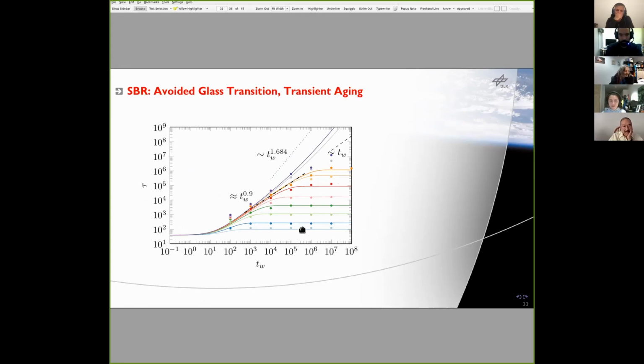And if I do that, basically nothing dramatically changes for the points where I quench to liquid states, because there in the end still ordinary MCT is good enough. But for the quenches into the glassy state, we get this. Of course, there are adjustable parameters here, as Tommaso was showing. So there's the delta sigma squared that you need to choose as an additional parameter here, essentially. But under plausible assumptions, you can make this work. And I think this is at least a qualitative statement that in principle, the deviations that we see here from the predicted hyperaging asymptote in the computer simulations can be explained by stochastic beta relaxation theory.